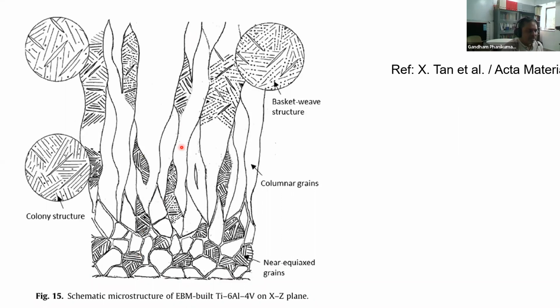So electron beam based directed energy build was done. And you see that at the bottom you have got some equiaxed grains, and then as it grows, you have got columnar grains. And then there are some regions which have what is called a basket weave structure, typical of alpha beta titanium alloys. And as you can make out, there is a heterogeneity of microstructure in this particular alloy.